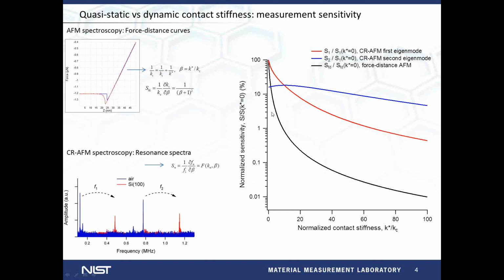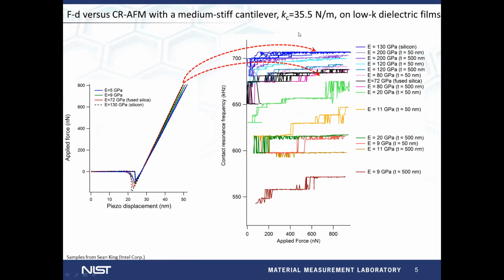Here the black curve is the sensitivity of the force distance curve as a function of normalized contact stiffness. And we see that this decays much more rapidly with increasing contact stiffness compared with contact resonance sensitivity here for the first two eigenmodes. It's known in force distance measurements that in order to do measurements on stiffer materials, we have to increase the cantilever stiffness, because then we push the measurement point into the region with higher sensitivity. But with contact resonance, this measurement sensitivity decays much slower, so we can look at stiffer materials with medium stiff cantilevers.